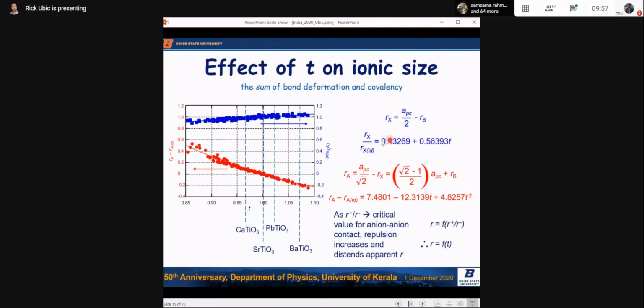All right. And down here, we have R_A minus R_A ideal. So R_A from geometry, this guy here, right? Just from the geometry of a cube, minus the Shannon size. So if R_A were the Shannon size, this would be a flat line at 0. The difference would be 0, right? But it's not. It has this negative slope. It's almost a line. You can pretty much describe it as a line, but it fits better as a quadratic. So we fit it as a quadratic. This is the equation that describes that red curve.